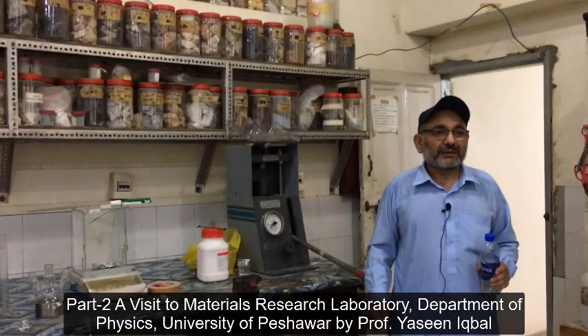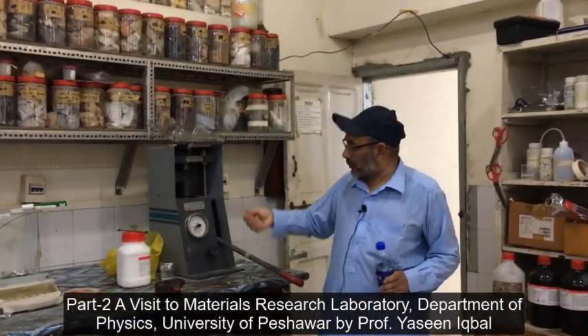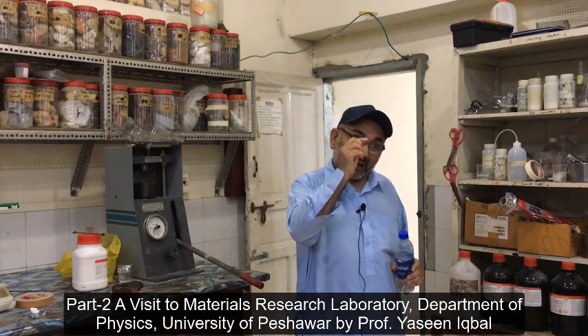Secondly, you are densifying the material. The powders are not dense. You press it, they become denser. But if you use much higher pressure, when you release it, the material will crack. So there is also an optimum level of pressure, and you will have to check.